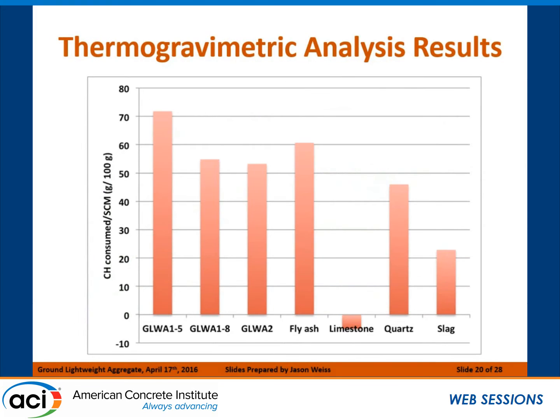If we look at the thermogravimetric analysis, again, we see a very different picture starting to emerge where we see a lot of materials that are consuming the calcium hydroxide, our ground lightweight aggregate, our fly ash, and we see the limestone actually giving back some of the calcium hydroxide in the system.